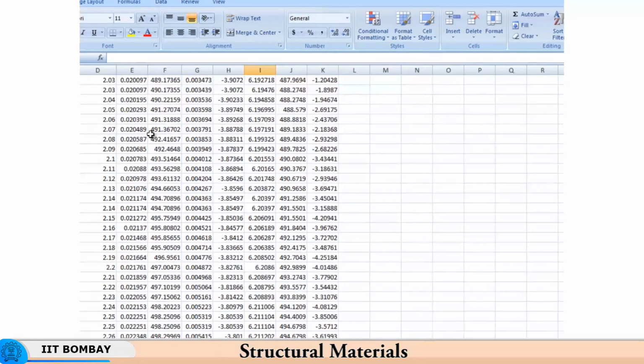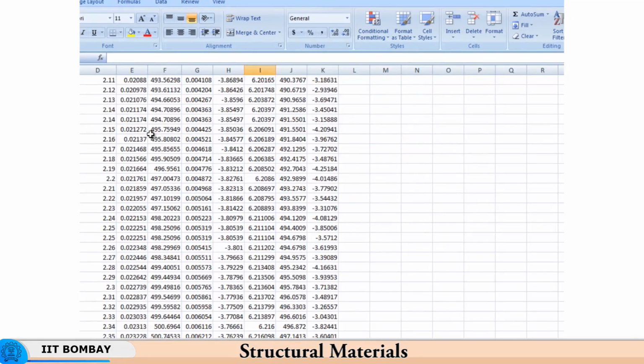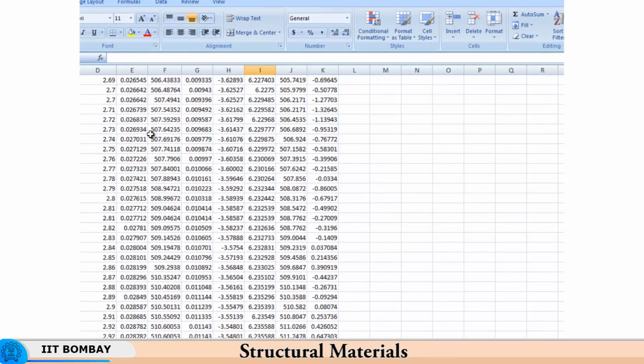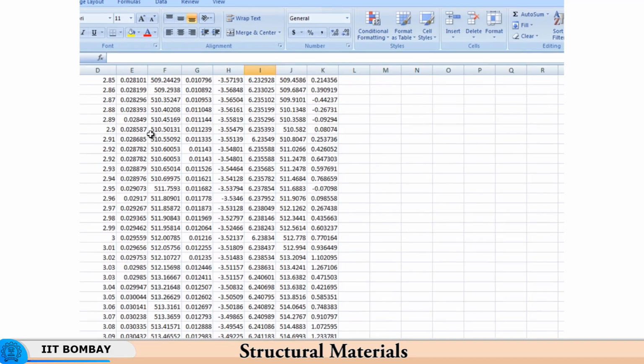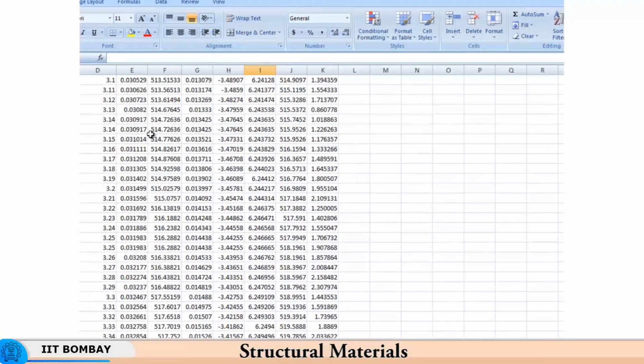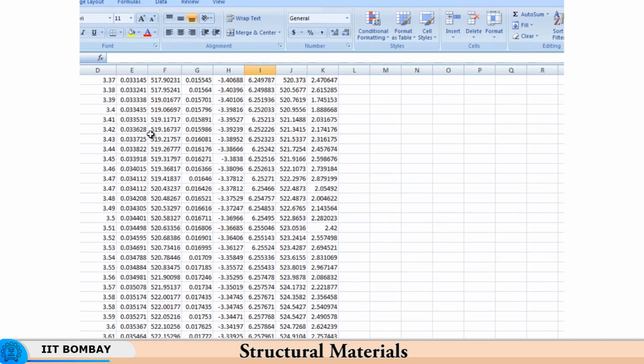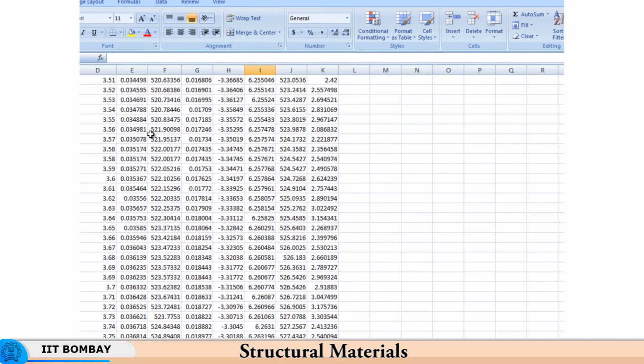it is appropriate to go beyond about 8% of true strain. So, if the strain is beyond 8%, then the error continues to decrease to a very small level. If you go down further, it will be a fraction of a percent. So, you have about 3 MPa in over 526 MPa of stress. So, it is hardly any error that is incurred.